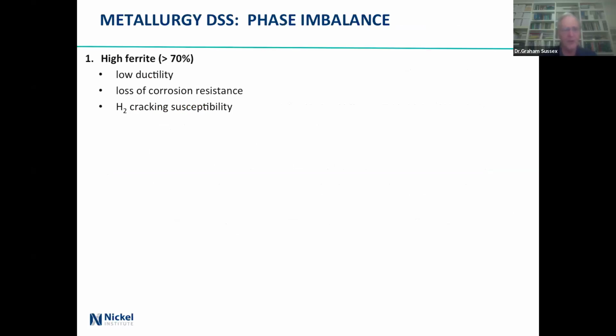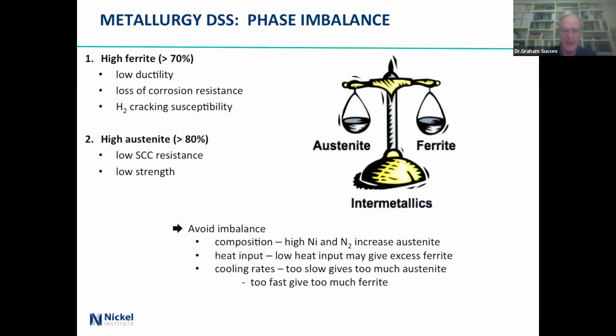If you're talking about high ferrite, okay, low ductility, loss of corrosion resistance, and cracking, hydrogen cracking. High austenite, low stress corrosion resistance, and usually low strength. You can balance it and keep it in the middle. In terms of composition, high nickel and high nitrogen will increase the austenite. If you want that, fine.